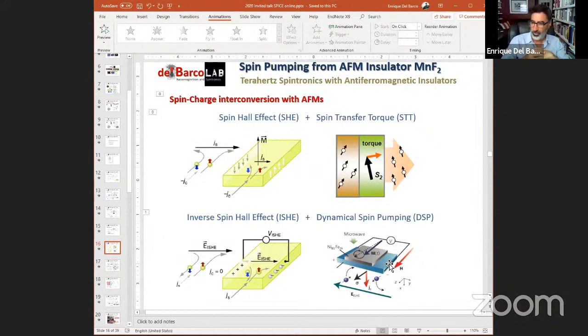So the electric current that we measure, the voltage that we measure, is proportional to the spin current that is being injected from the antiferromagnet undergoing antiferromagnetic resonance into platinum.